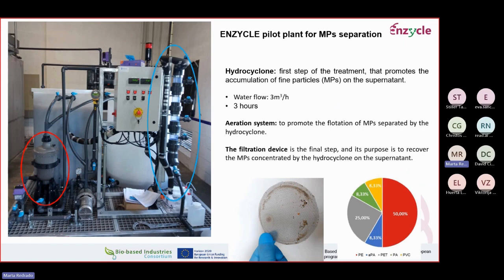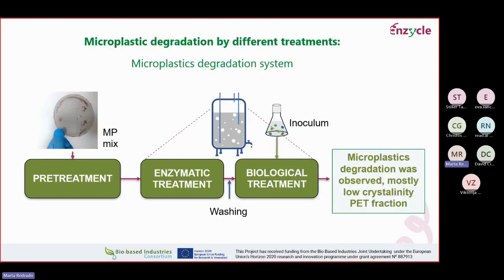And we also performed, of course, some analysis to identify which compositions of the microplastics were present. So we found out that most of the microplastic present was polyethylene, and there were also fractions of polyamide, PET, and PVC. So what we did with these microplastics, once they were recovered, was to subject them to different degradation systems. Actually, we were not able to recover so many microplastics from these wastewater treatments, so we were using a model microplastic mix that we were producing in Enzycle.